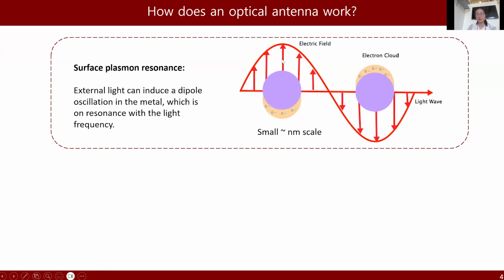The light consists of an oscillating electric field, and that electric field can induce a dipole inside this antenna, which is a separation of charges. This is followed by a collective oscillation of free electrons inside this metal. When the incoming light frequency matches the plasmonic oscillation frequency, which is the so-called surface plasmonic resonance, it allows for a strong absorption of the incident light and concentrates its energy to a strong localized near field.